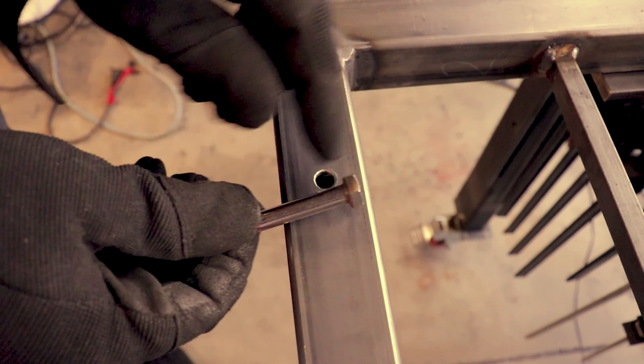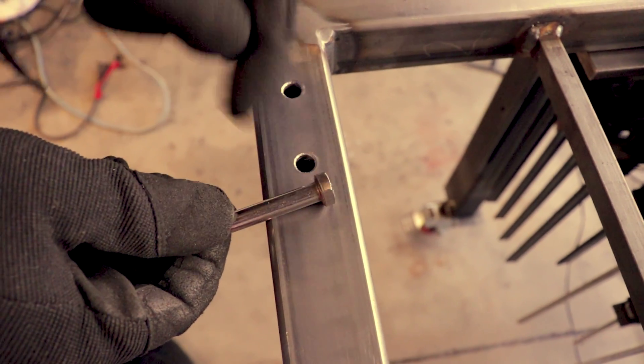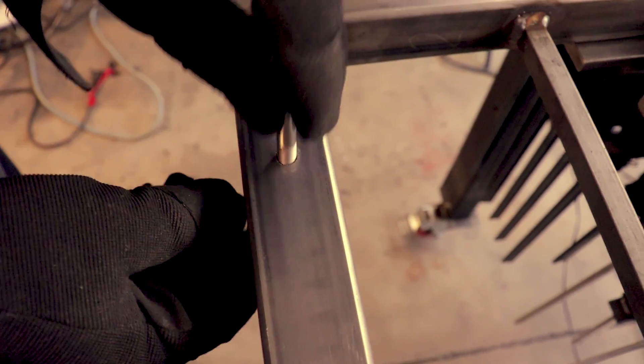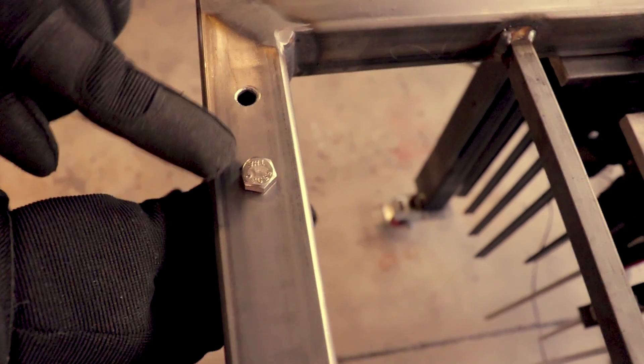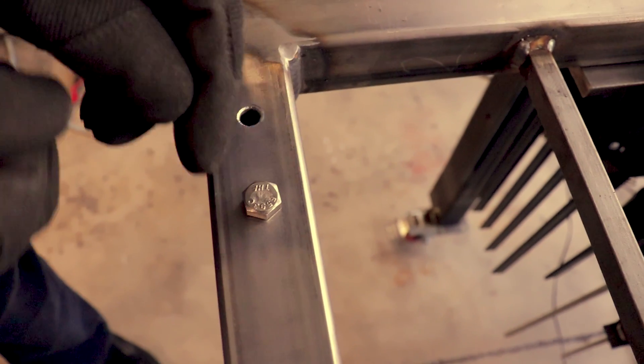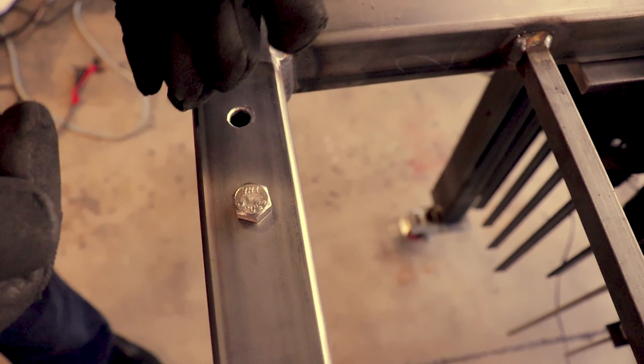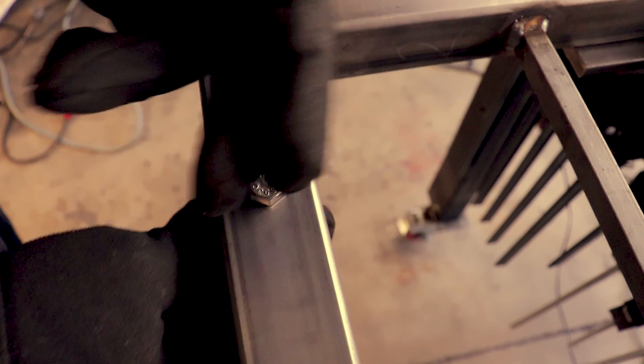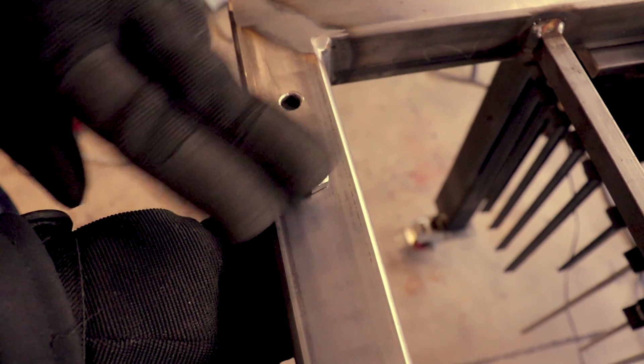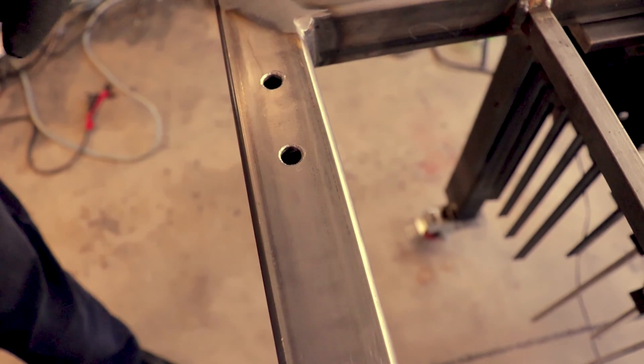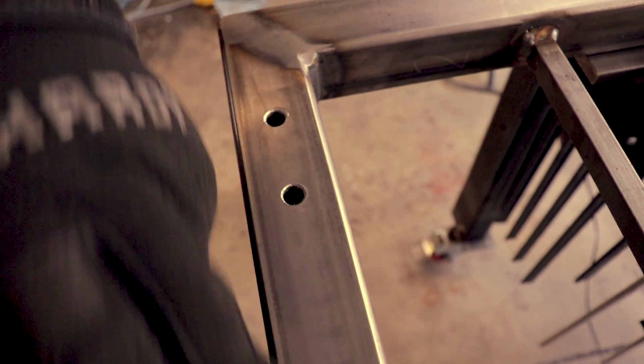So what I'm going to be doing is hacking the heads off of these bolts, recessing them down in there below flush and then plug welding or rosette welding, whatever you like to call it, and filling it above flush. That way I can grind it down and it'll be smooth like this.